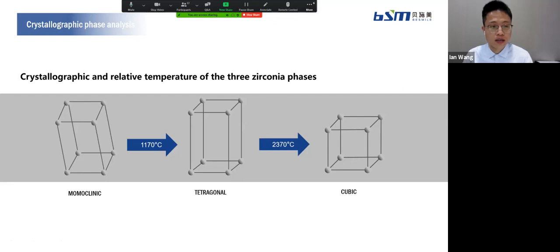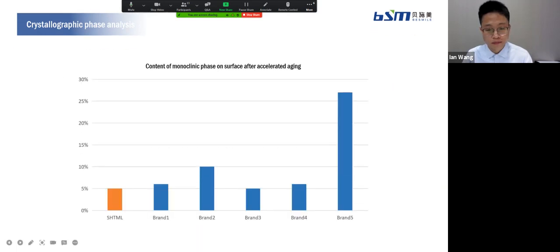So we can test the content of monoclinic phase on the surface after accelerated aging to check the stability of zirconia blanks. And so we did a test on this, and this is the result. And we can see most brands have a very high stability, because after accelerated aging, the content of monoclinic phase on the surface is very low, and that includes our newly upgraded SHTML. And brand 5 has a very high value, which shows it has a bad stability.